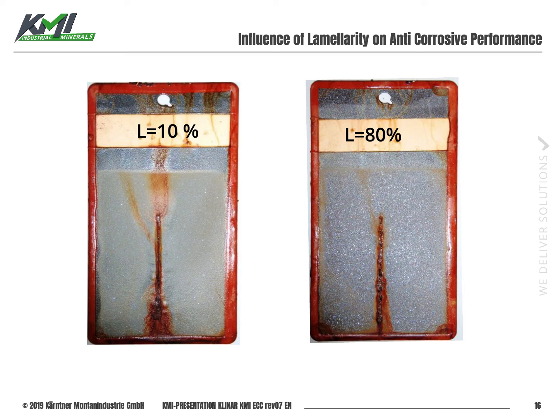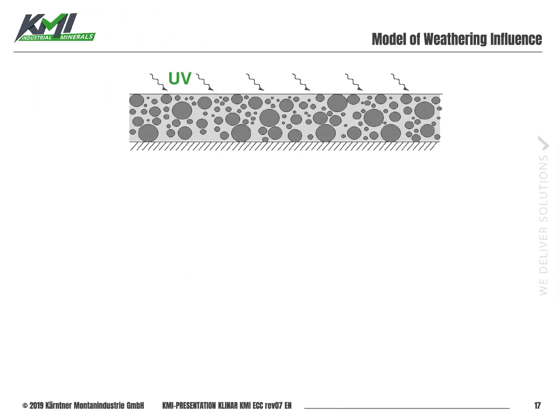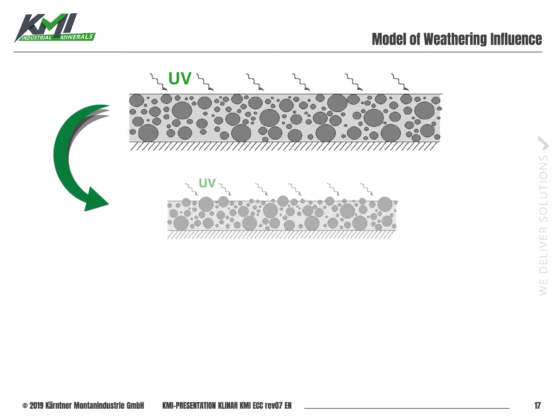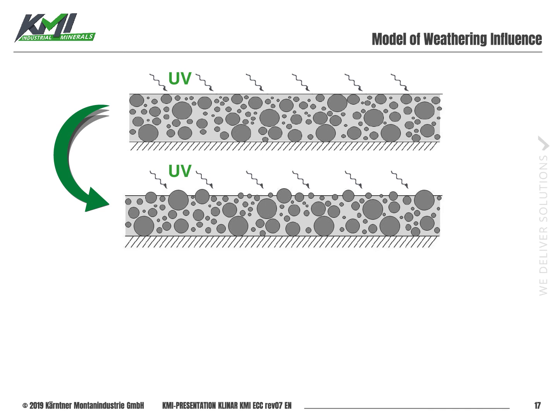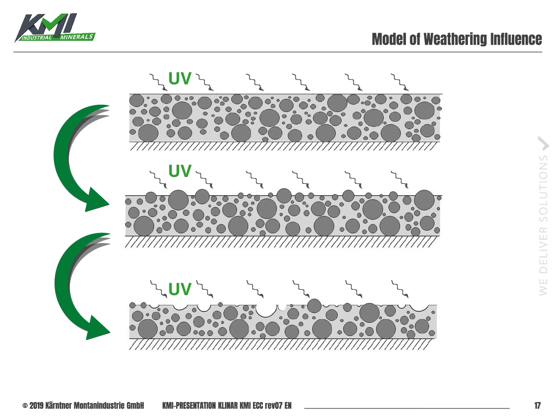What you can see here on the left hand side is a lot more film degradation and delamination and rusting around the scribe compared to the right hand side picture, where you have almost no film degradation and also a very stable situation around the scribe. The reason for that is shown in the following model. When you work with a more granular micaceous iron oxide product and you have UV radiation on your coating, then due to the film degradation you will lose the first layer of polymer, then the granules will begin to stick out of the coating, and as a last step the granules will break out of the coating. You create pinholes, the UV radiation can enter these pinholes and the degradation goes on and on.